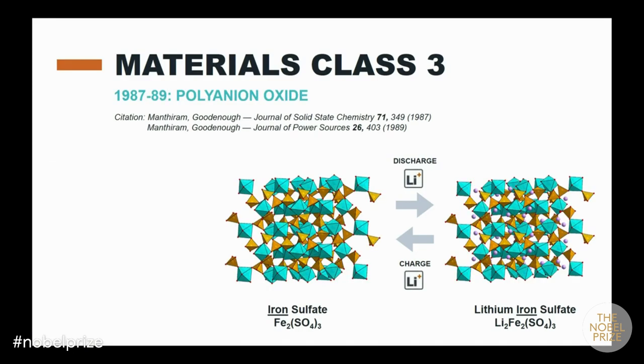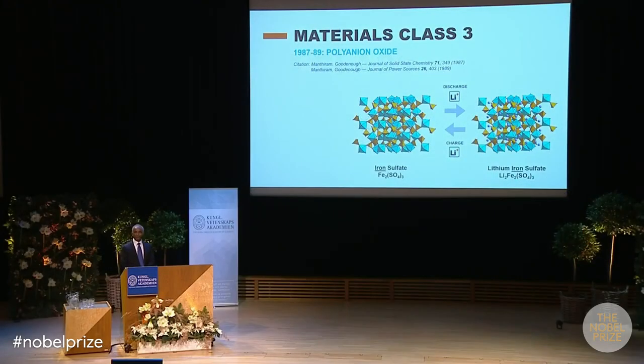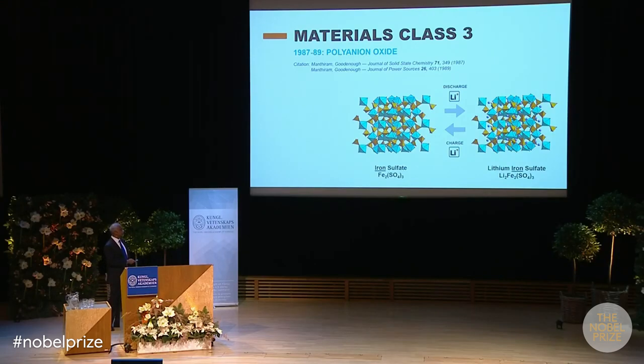The two classes of materials we saw earlier were simple oxides. So they are prone to lose oxygen from the lattice under the conditions of short circuiting or higher temperatures. So the third series of oxides explored were polyanion oxide like iron sulfate, in which the oxygen is bonded very tightly to the sulfur anion in the polyanion, so they offered better thermal stability.